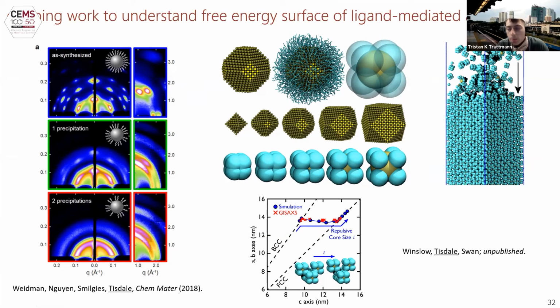So by that hypothesis, if you were to grow these crystals in an ahedral environment where they're perfectly spherical, would you still get this orientation effect? I do not think you'll get the orientation effect. I skipped over some of my literature review. You still get this big interplay between BCC and FCC.